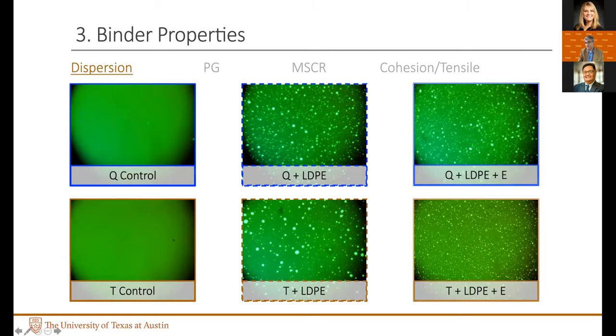Now, it is also interesting that when we add the terpolymer, that terpolymer helps disperse some of that plastic even better. So you see a significant improvement in the dispersion as you go from the images in the middle to the images on the right. You would see that the particle size on average is reduced. It's much more uniform. It's not a fully smooth blend yet, but it has significantly improved in dispersion. And it's always better to have smaller, finer, more dispersed particles instead of larger blobs accumulating. So in that sense, that terpolymer did clearly show visually some benefits here.